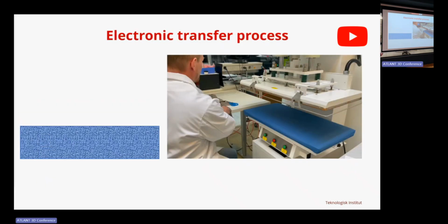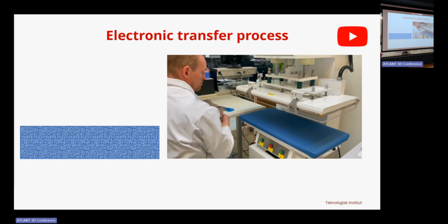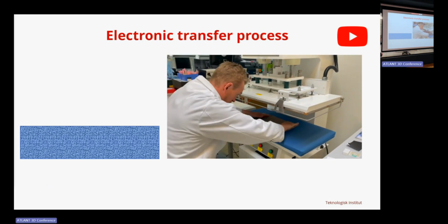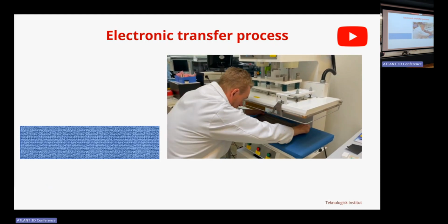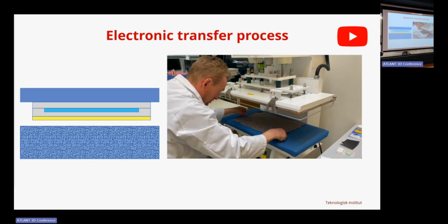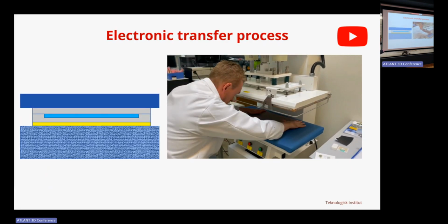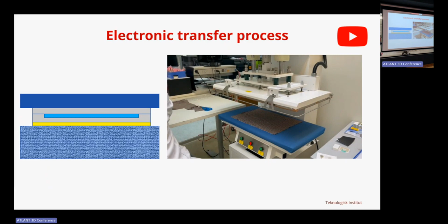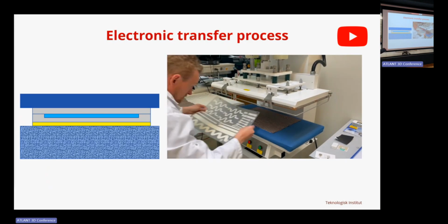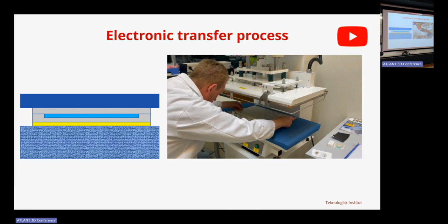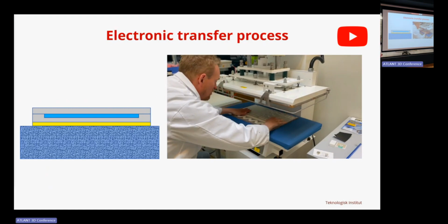Then we do the transfer process where we have the fabric, and I'll try to speed this one up. We just use a heat transfer. We take the foil we just printed and put it into contact with the fabric. We apply a little bit of pressure and some heat. The adhesive then melts into the fabric, and then you rip off the foil. And that's what's going to happen here.